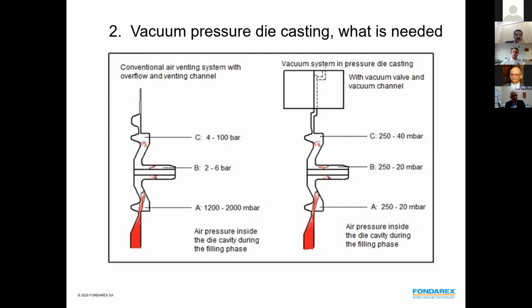So now this is why FONDAREX actually invented the vacuum venting. Was it back in 52 or something? So that's almost 70 years ago, when the first vacuum system was invented. And the target is, once the alloy gets to the gate, that we have reduced the pressure inside the cavity to maybe 300, 200, 100 millibar.